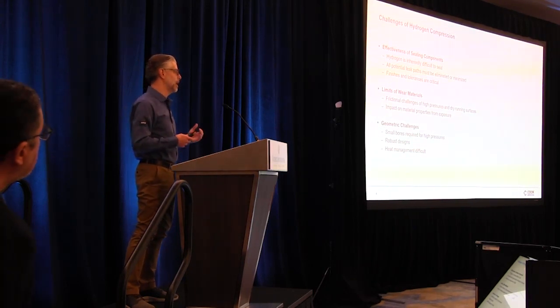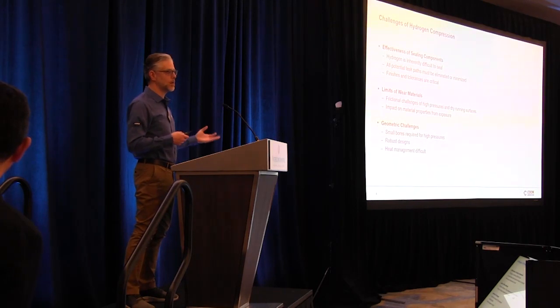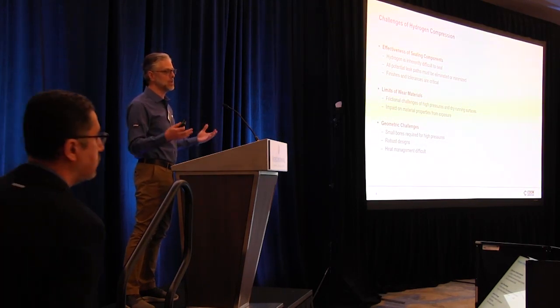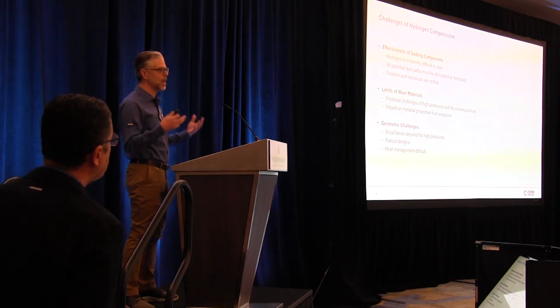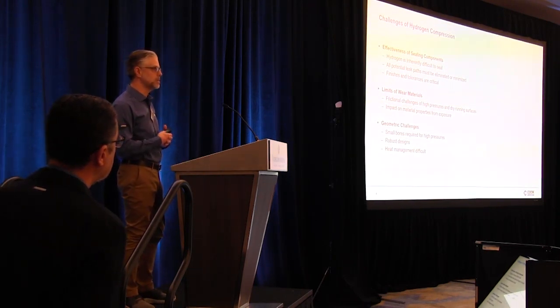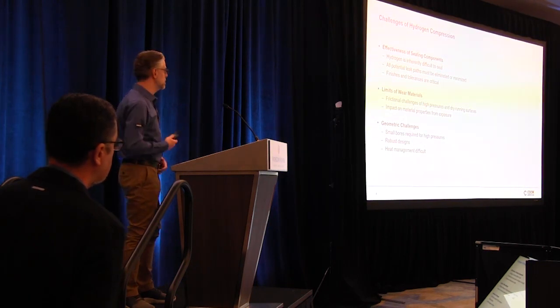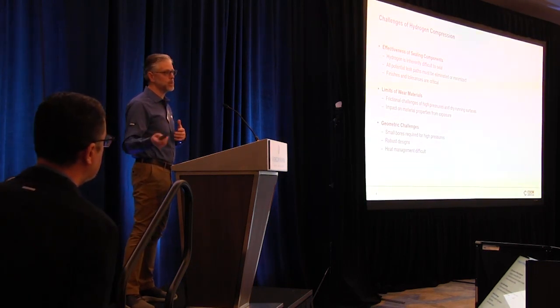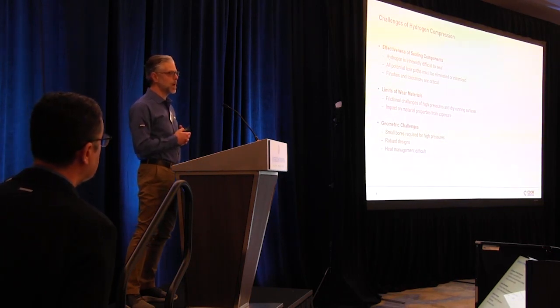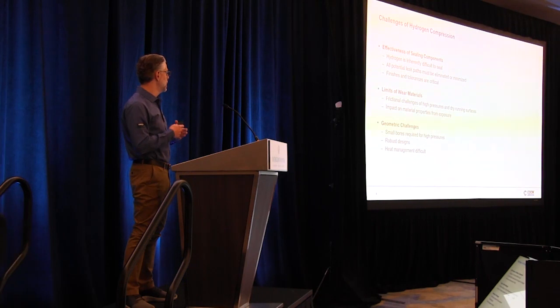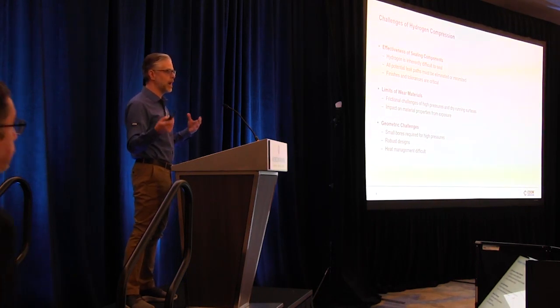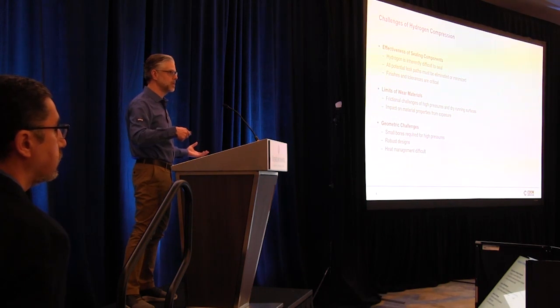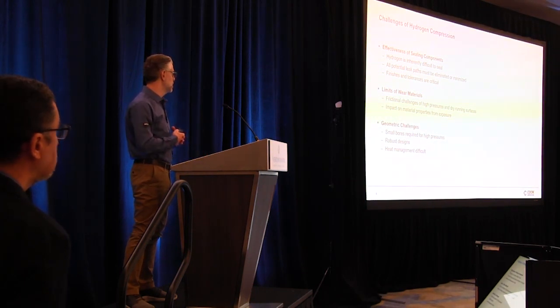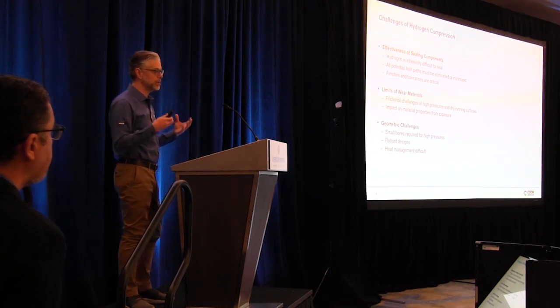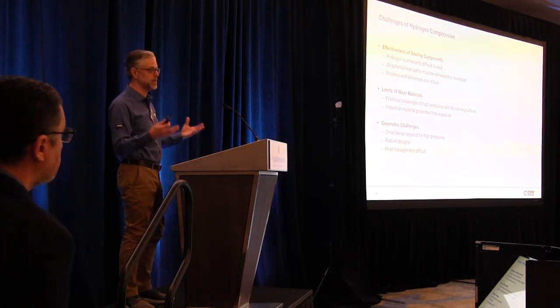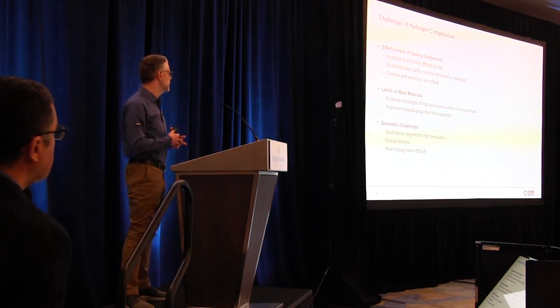We have to look very carefully at clearances, tolerances of fit, surface finish. All of these things as we're designing our seal parts become a lot more critical. So our specifications around these are evolving as we move into this market. The limits of the wear materials, and this really is what Burak will go into a little bit more detail on, but the frictional challenges of high pressure and non-lube running surfaces are very challenging here. And then there's even an impact on just the material from exposure to high pressure hydrogen. How does that change the material inherently, right?